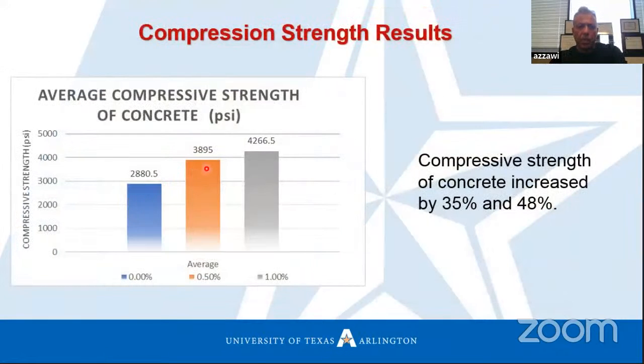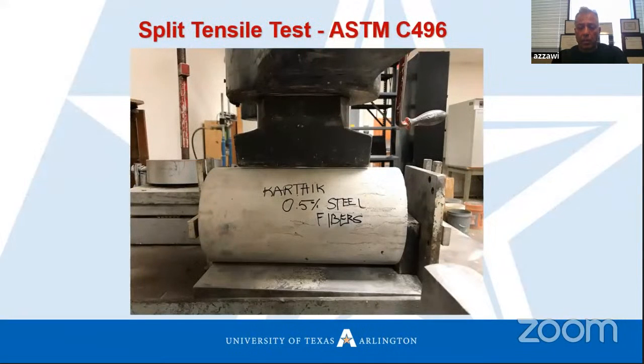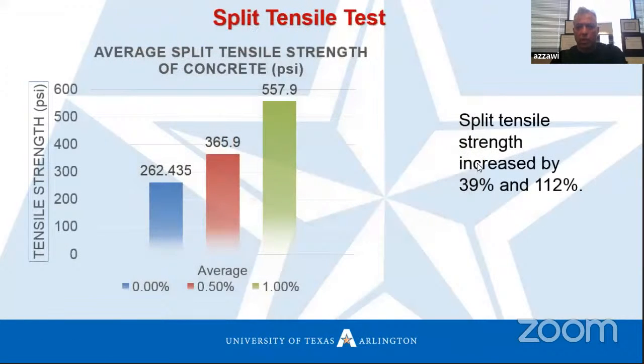In fact, with the steel fiber, we have an increase in the compression strength as we increase the steel ratio. But the remarkable improvement is in the tensile strength, as we see here. So the split tensile strength increased around 40% to 112% compared with concrete without any steel fiber.